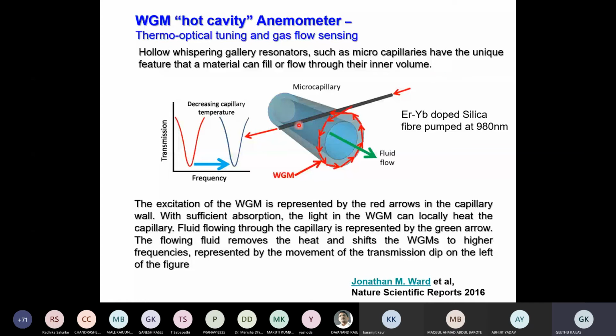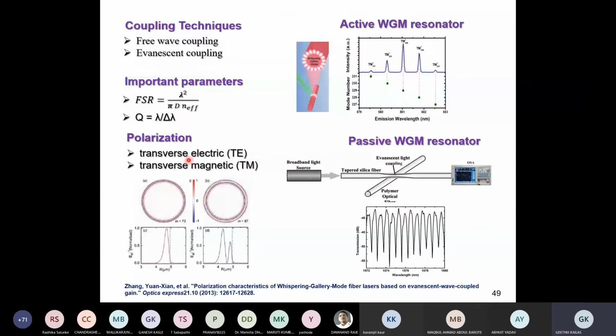So this is a fiber which is used to excite the WGM in the capillary. So it can be an evanescent wave coupling from here. So in the transmitted spectrum, you will have a dip because corresponding to this WGM, one wavelength is actually dropped. And this is very much useful for acting as a flow sensor, something like an anemometer. So the local heating by the WGM controls the liquid flow. So it can be a flow sensor.